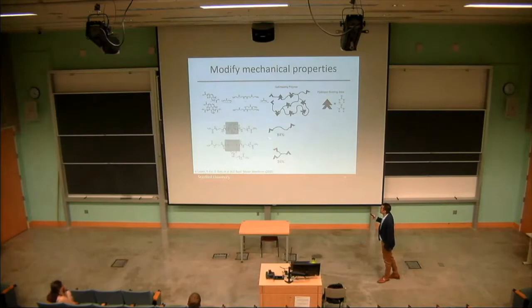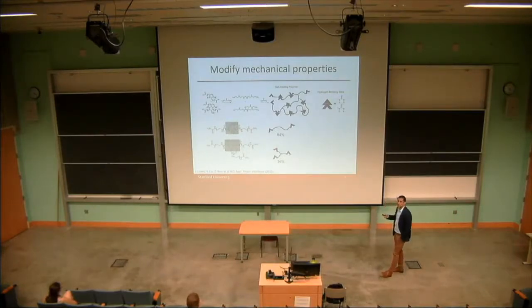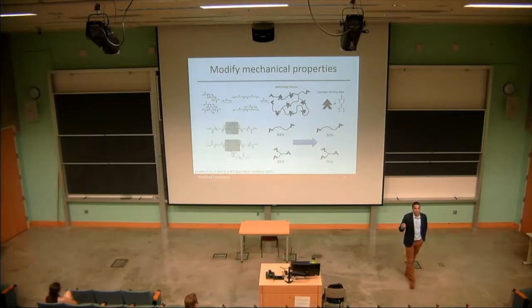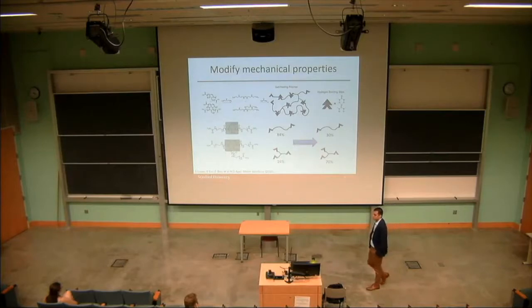As I mentioned, it's mostly this diacid material that we start with, so it gives us a difunctional hydrogen bonding group, and you can imagine this associates with other ones to form mostly linear chains. But then we add in a little bit of this trifunctional group, and what that does is it allows us to form this network, and that gives us our mechanical structure. So we have a gelled material that then behaves a little bit more elastically than just a purely linear polymer. But what we can do is change the ratio of these two, and we can go all the way up to about 70% of this trifunctional material, giving us very, very different mechanical properties without changing the chemistry at all. And so this allows us to probe with high precision the mechanics, but again, without changing the chemistry in any way.